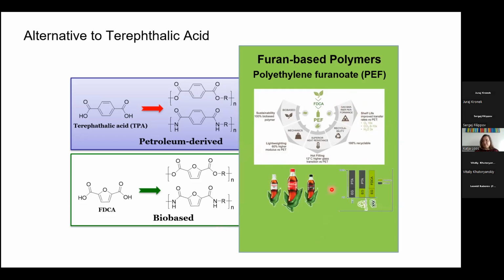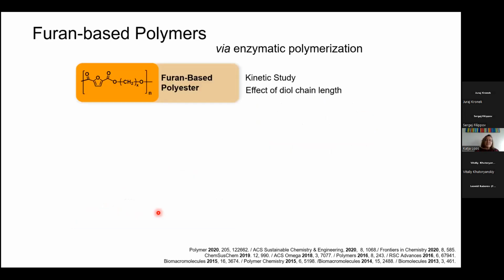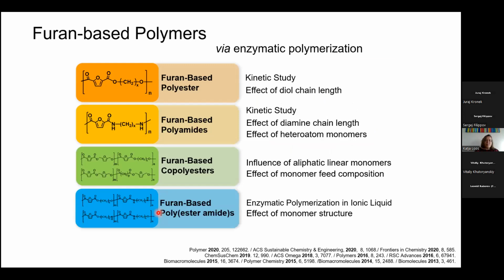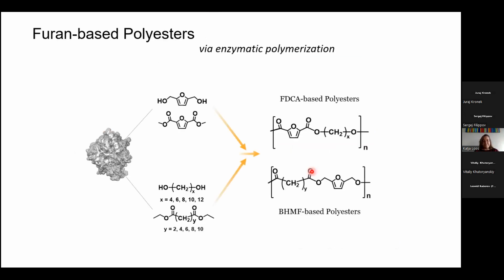And you might have seen these commercials from Coca-Cola, the plant-based bottles, but there is at the moment not a single plastic bottle out there which is pure PEF, because the production capacity in the whole world is not very high. And they all have problems with this yellow discoloration and decarboxylation in the polycondensation because of the too high temperatures for this monomer, and the diol they cannot even handle. So we started with furan-based polyesters, polyamides, copolyesters, and polyester amides. And you see we did different things in these polymer classes, and I want to show you a few of them.